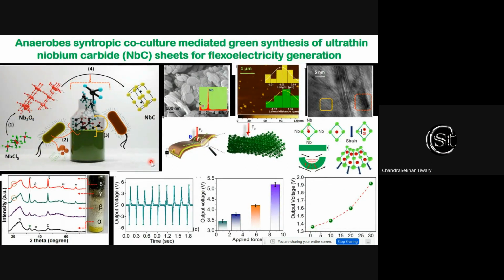Also, we can extend this to make some of the important carbides which are utilized for aerospace application. So if you know about titanium, tantalum carbides or even niobium carbide, they are very good for high temperature application, but processing them is very difficult because it takes a lot of energy to make them. Now we can take niobium salt and start with niobium oxide, treat it in anaerobic conditions in the presence of microbes, and you can see in the scanning electron microscope here and also AFM, you can make almost similar size and thickness niobium carbide from niobium oxide, which is generally found in nature.